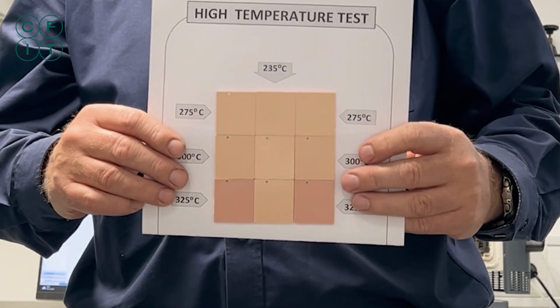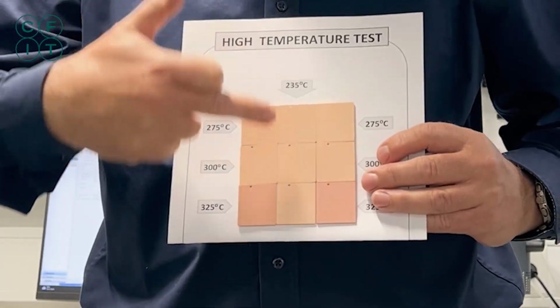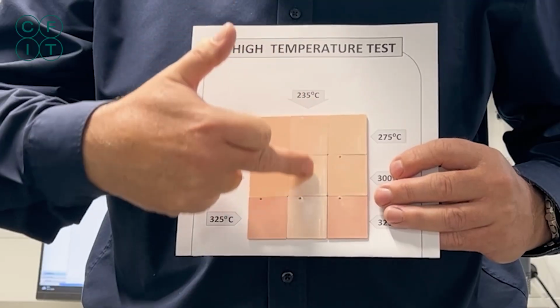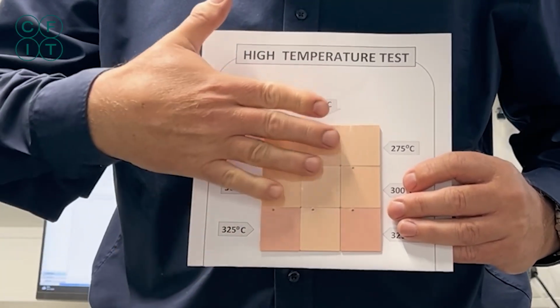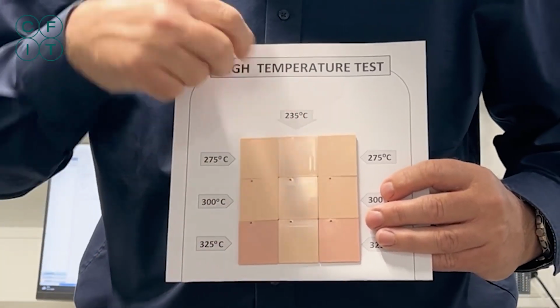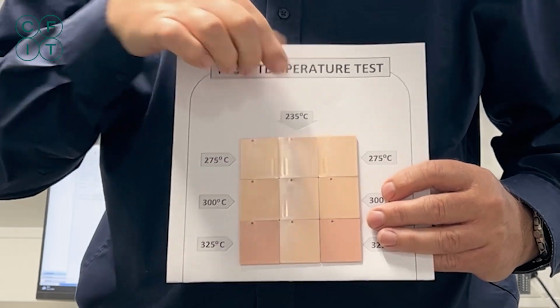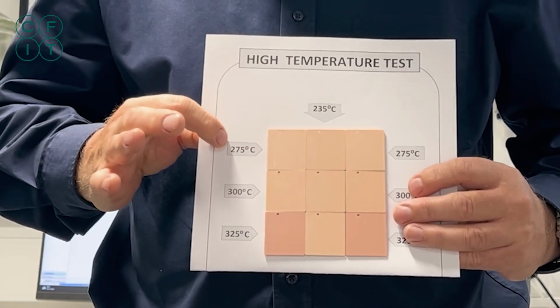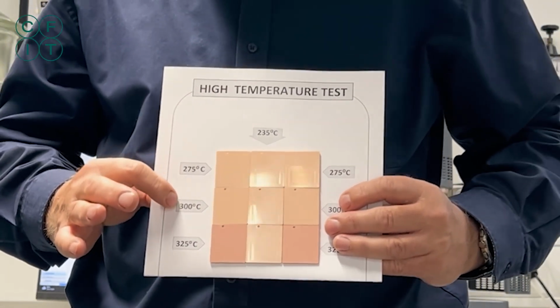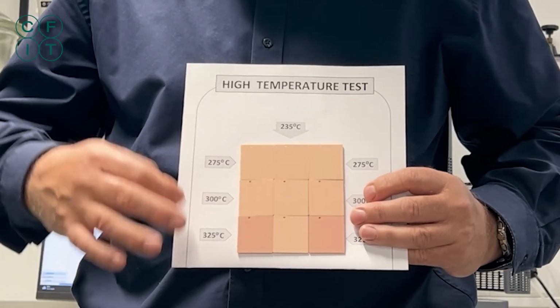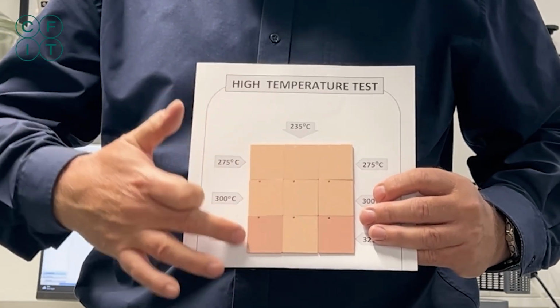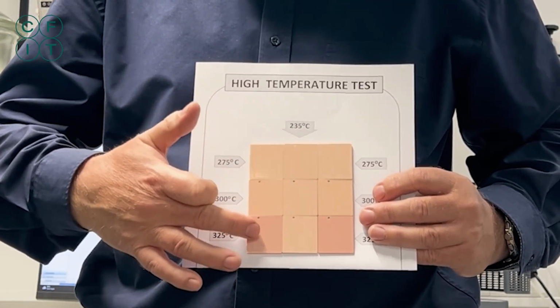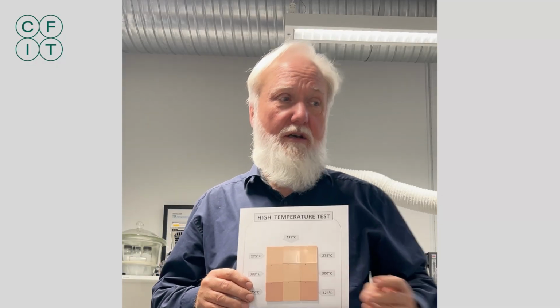And here we have an example where we by purpose have compared this color molded at the right temperature, 235 degrees, and then we have elevated the temperature to 275, 300 and 325 degrees, and you can see how different this color is. This is not just another color. And these temperatures are not unrealistic to reach in these big inlet systems.